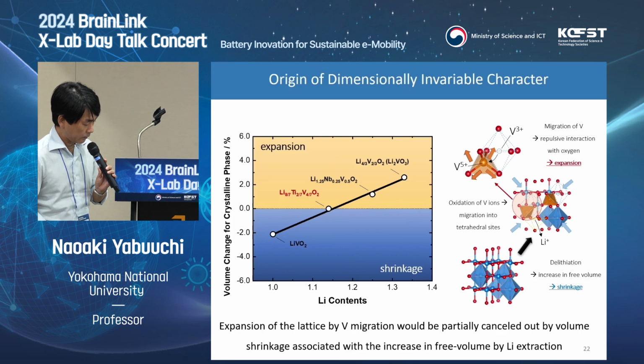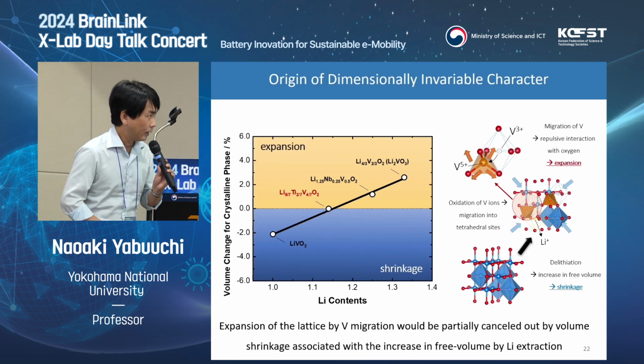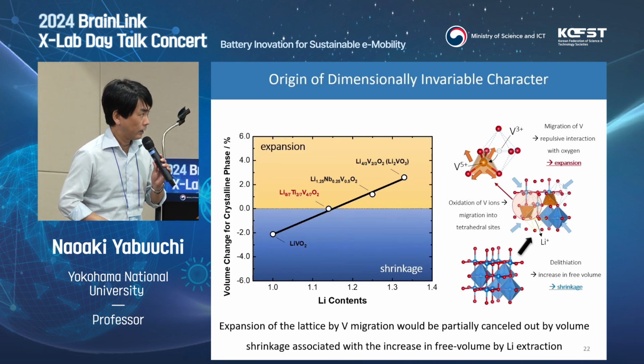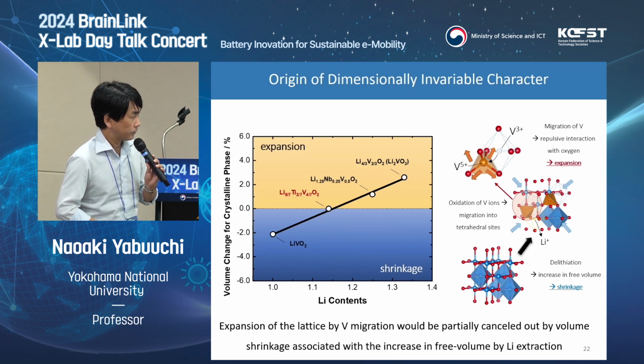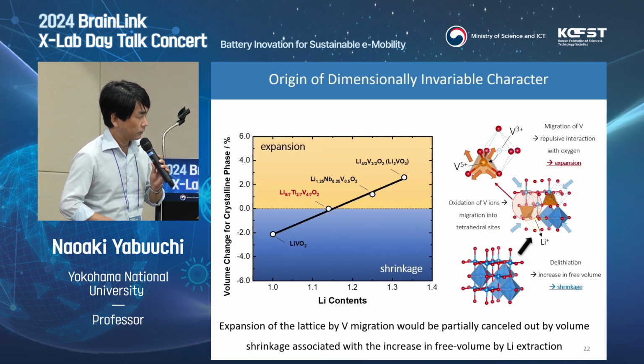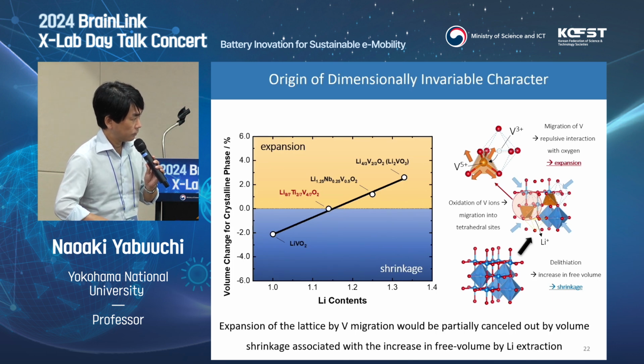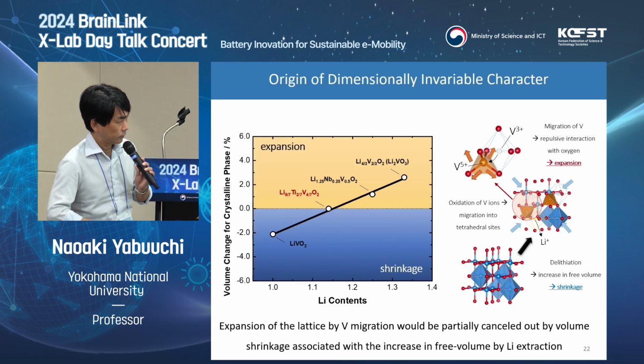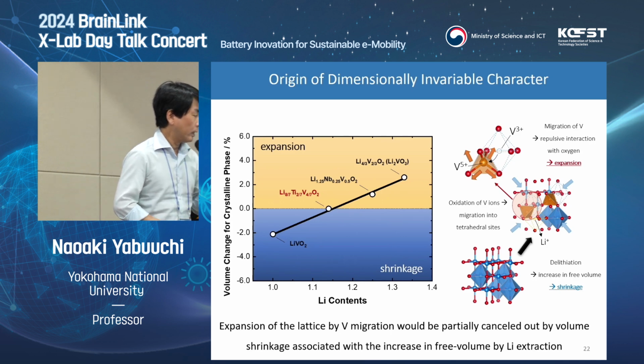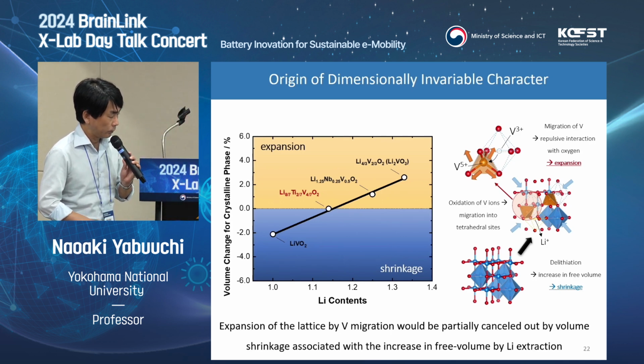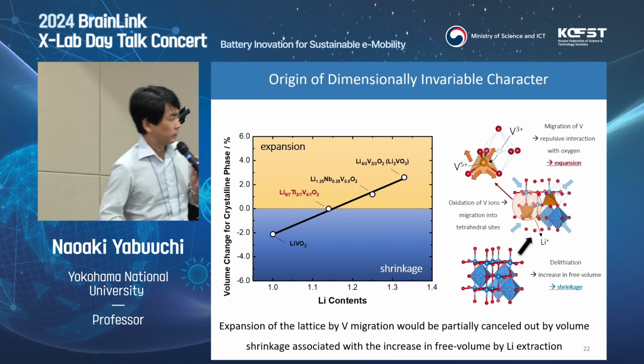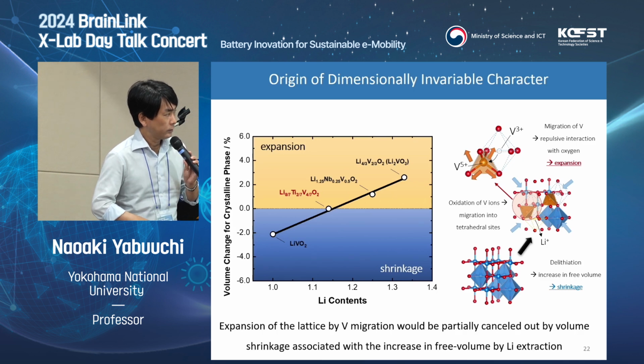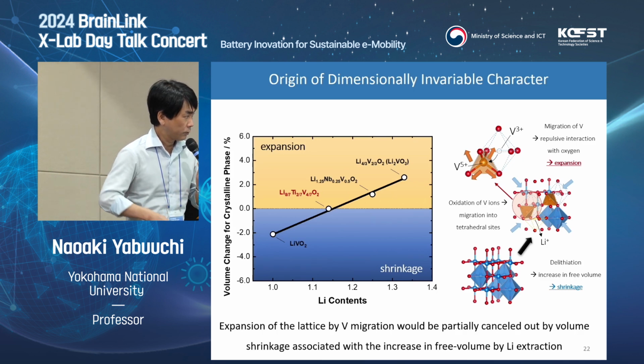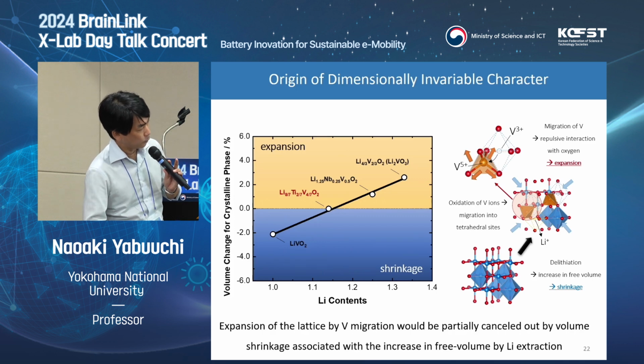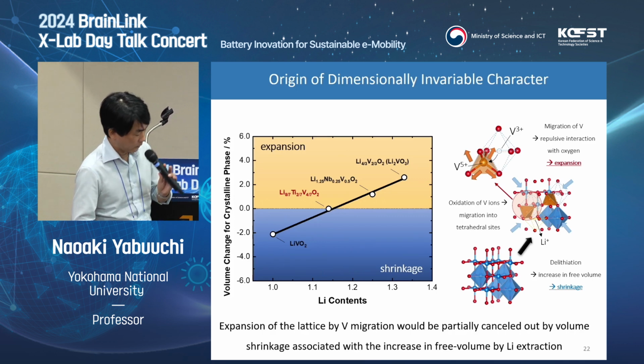Let me explain by using this graph. We checked the volume change over different vanadium-based rock salt type materials, based on the vanadium ions, and also the lithium contents are different. Here are stoichiometric samples and also lithium-rich samples. When we observe the volume change for rock salt LiVO2, you can observe a volume shrinkage after charging, as expected, because the oxidation of vanadium ions results in more shrinkage, and also extraction of lithium ions increases the free volume in the structure, resulting in a shrinkage, as expected.